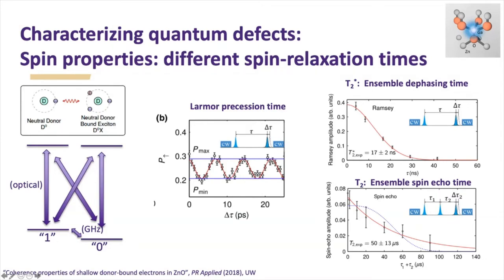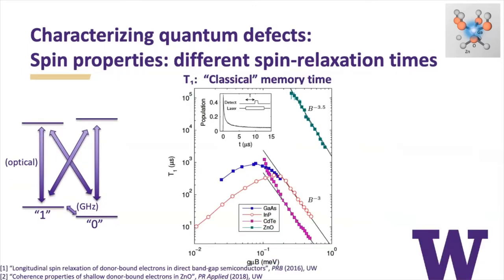And if we want to ask what is the fundamental limit, the fundamental limit that the spin coherence time or this quantum memory time cannot exceed is the classical relaxation time. That's saying, if I create a one state or initialize just into the classical state one, how long does it take to relax to zero? Or if I initiate in zero, how long does it take to do it in one? And what you can see here is that for these types of defects, gallium arsenide, indium phosphide, cadmium telluride, the donors in these semiconductors, we can maximize T1 at around 1 millisecond. For zinc oxide, and this is one reason why I'm studying zinc oxide, this is now at 500 milliseconds. So this is the fundamental limit. We're not there yet in terms of quantum memory time.